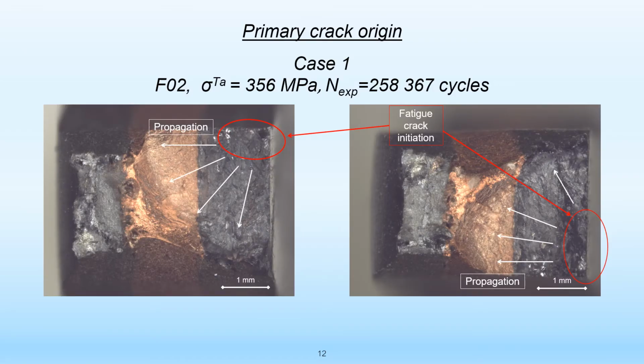Here is the example of specimen 2 from case 1, with the maximum load in tantalum layer of 356 megapascals and a fatigue life of nearly 260,000 cycles. In the picture, you can see a primary crack origin identified in the region circled with a red color. Crack paths were marked with white arrows.